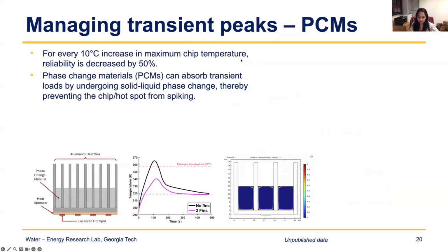And then to work with the transient peaks that occur. So if you have a large spike in power, a thermal system cannot respond quickly. A thermal system takes longer to respond. And so you need some kind of a buffer to take the thermal load and then dissipate it over a longer time scale. So phase change materials are really suitable for this, because by definition, when you have phase change happening, you maintain the temperature. So it'll keep the temperature at the safe operating limit and acts just as a thermal buffer to undergo melting. And then that melted phase change material has to re-solidify by rejecting the heat, but you're essentially just increasing the time scale.